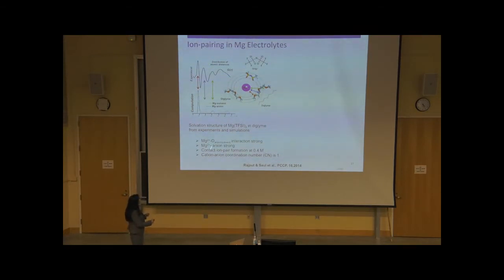By contact ion pair, I mean that there is at least one anion in the first solvation shell around the cation magnesium, such that the coordination number of cation and anion is 1. And why I stressed 0.4 molar is because this does not happen in lithium electrolytes, because you don't form any contact ion pairs even at 1 molar concentration. Just to give you a little bit of an idea about the terminology, when 2 ions are very well separated in the solution, they are called free ions. When the ions share 1 or 2 solvent molecules such that the coordination number of cation and anion is between 0 and 1, they're called solvent-separated ion pairs. When the coordination number is between 1 and 2, it's called contact ion pairs. And when you have more than 2 anions, they're called aggregates.